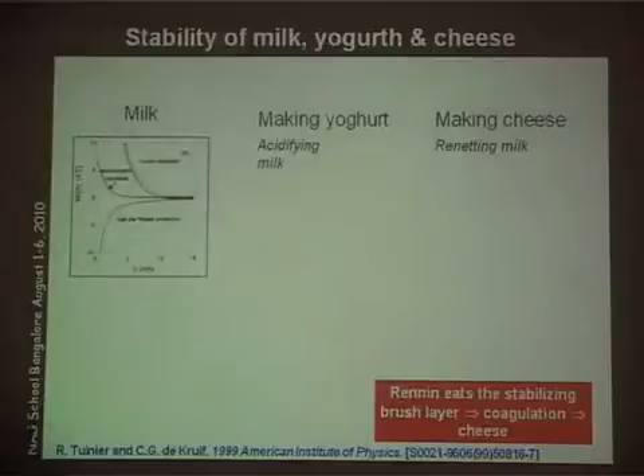Now, when we think of milk, sorry that the figure is such poor quality, but I couldn't improve it. When you look at milk, this is the interaction potential. Here is zero. Here is the separation between the micelles. That would be the pure van der Waals attraction. This is the Coulomb steric repulsion, and that's the overall repulsion. So milk is stable over a long time, unless it goes off and bugs digest it, and it's not so nice. We have a clearly overall repulsive interaction between the micelles, and that's why milk is whitish.